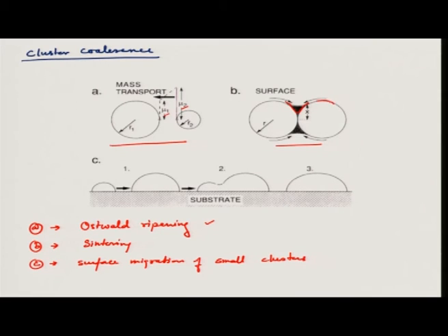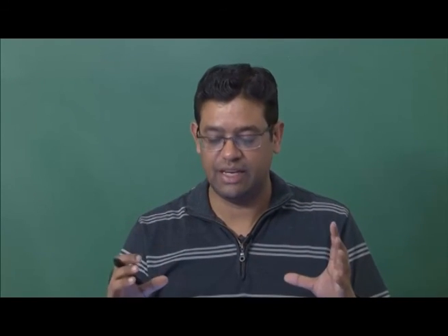It is shown that the energy of atoms on a convex surface is higher than on a concave surface. So atoms will tend to move towards this neck region from both, and slowly they will fuse and form one stable, larger nucleus. This is how different nuclei merge together.